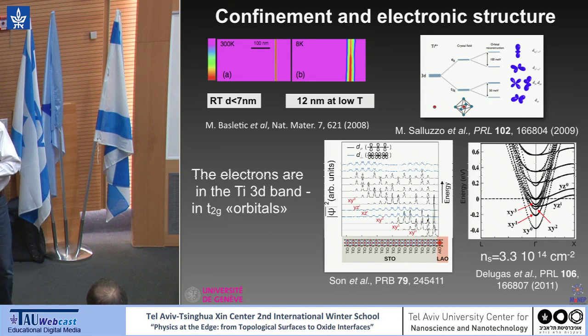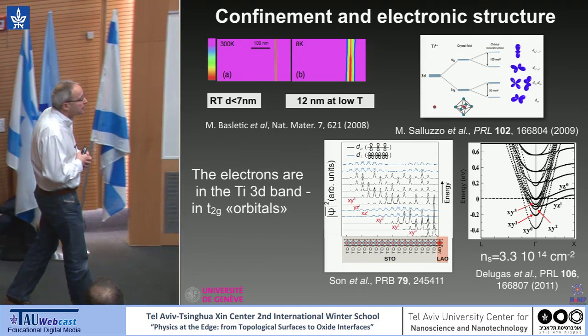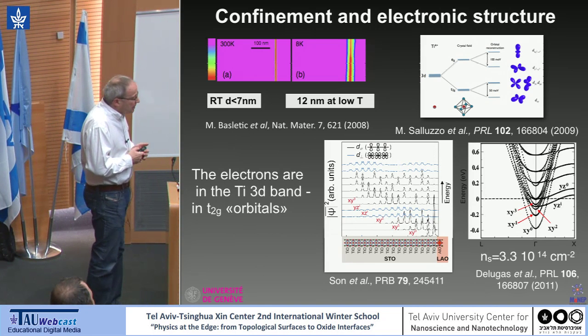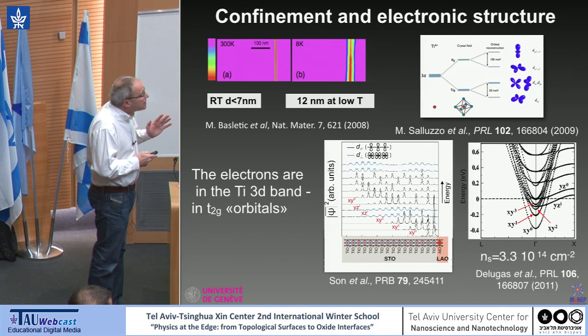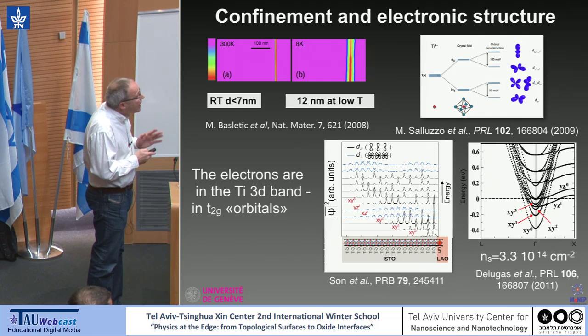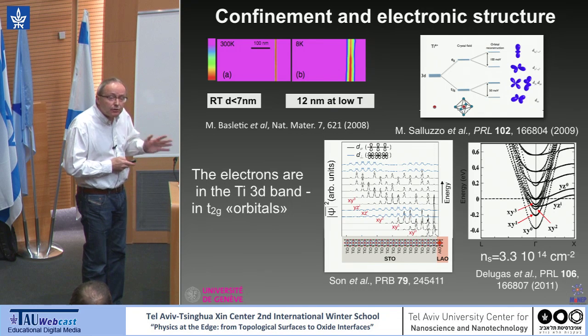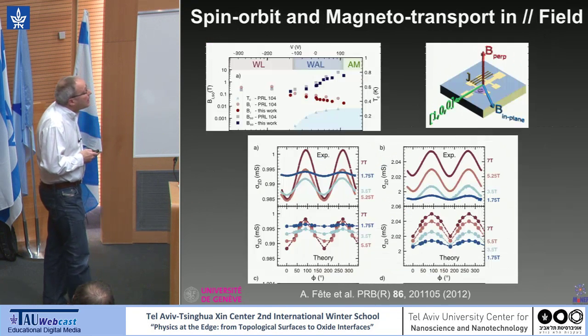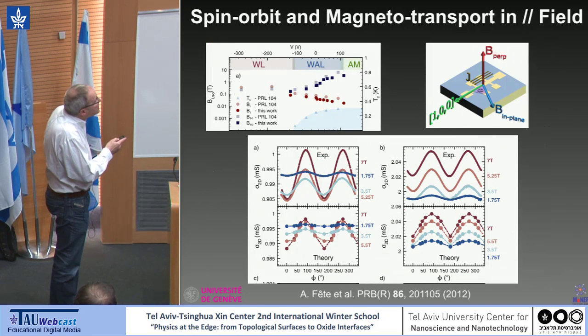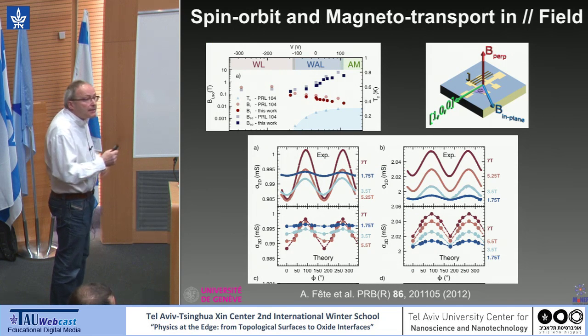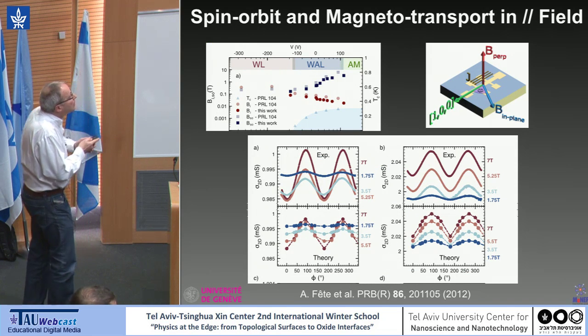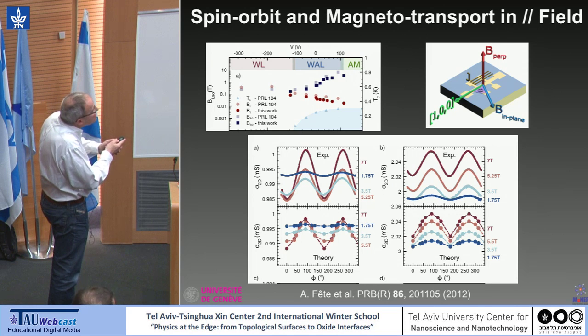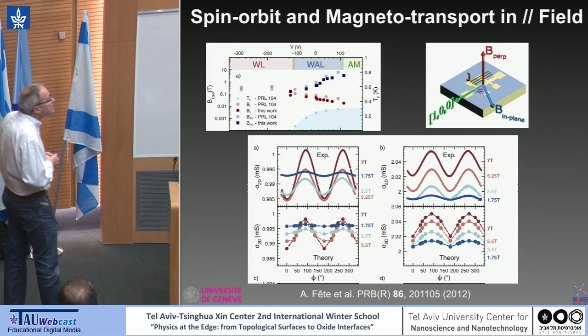From tunneling experiment, and and from Tc with a rough estimate, but Mannhart, I will show you, has made some tunneling experiment. I'm not mentioning this here in detail, but we have magneto-transport evidence, and several groups have been working on this to show that in this region of the phase diagram we start to have multiband transport. Now not everyone agrees, or not all the experiments agree.